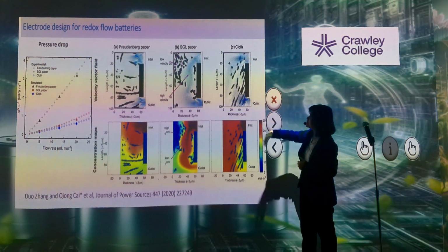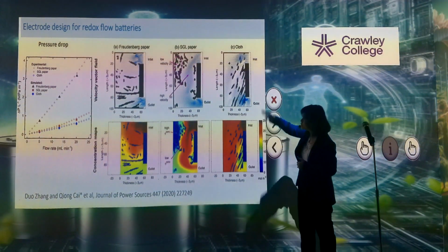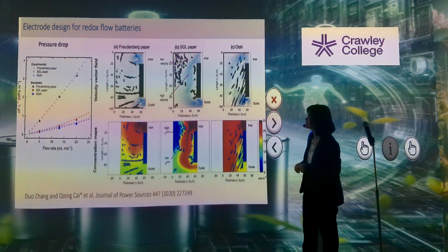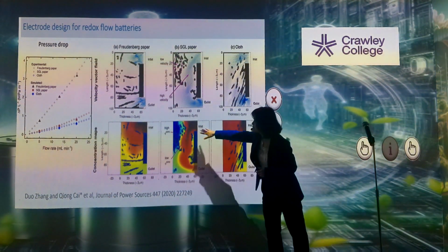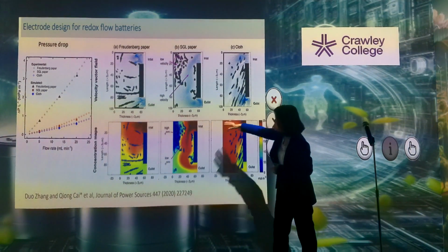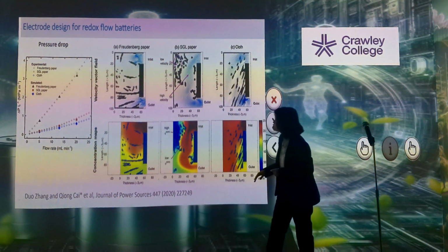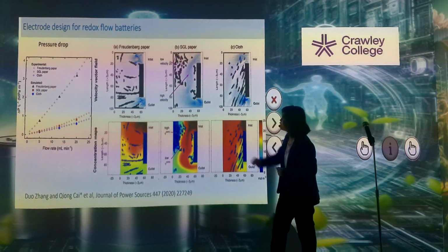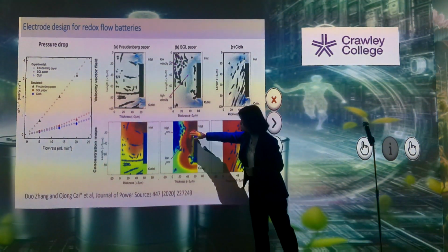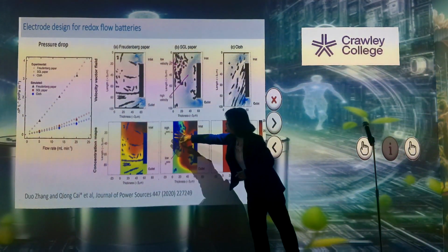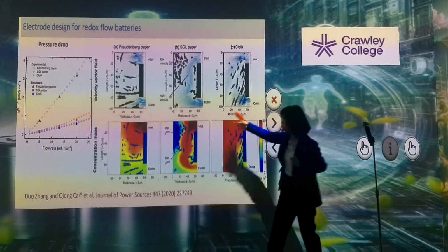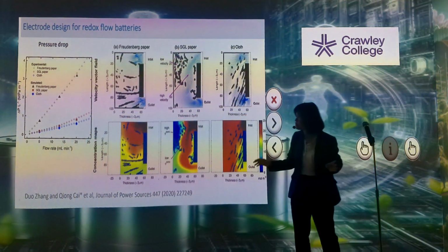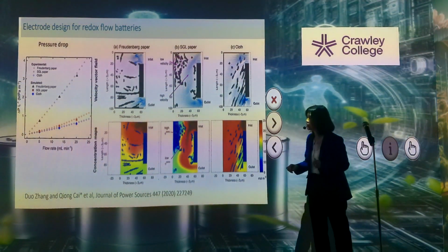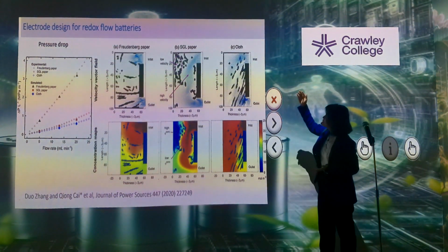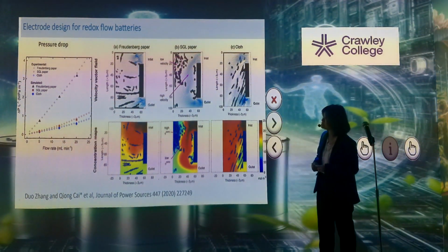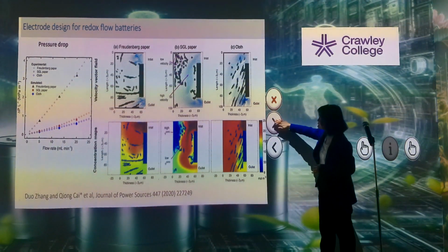And then when we look at how the electrolyte distributes within the electrode, we found that this SGL paper, so remember it gives a low pressure drop, but because of the random pore size distribution, part of the structure becomes inaccessible to the liquid electrolyte, so you have a very big concentration gradient across the structure. That is not good because it will give you very high concentration overpotential. So in conclusion then, we think carbon cloth is the best candidate for this type of batteries.